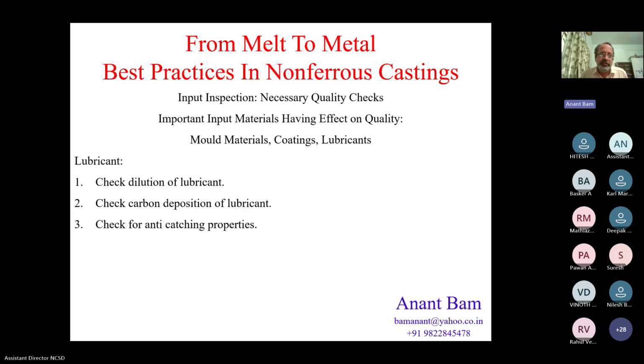When a system was set up of measuring the mother lubricant, measuring the diluting water, measuring the TDS of the diluting water, quality of the water, and using filtration before passing it onto the lubricant pump, these defects were gone. Next slide, please.